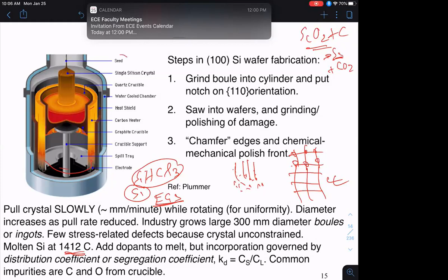And in that, you then take the single crystal seed, which should be a tiny region which has nice crystalline arrangements. Okay. And you momentarily dip it into this molten silicon, and you immediately pull it back so that the molten silicon is drawn out by surface tension forces. As it's drawn out of the molten silicon, it cools by radiative cooling, and it crystallizes, having the same orientation as the seed crystal. Okay, I guess I should show it down below. So I'm growing this crystal in the cylindrical shape below the seed crystal. Now, to make things uniform, as you pull it, you tend to rotate the crucible, and you counter-rotate the seed, the crystal that I'm growing.